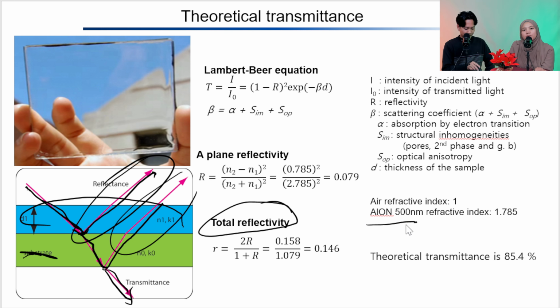And we can see here, as I mentioned, when we use... You talk about thickness. Yeah, it will be reduced. So even with fewer layers of the transparent gamma AlON, you can have a higher protection level compared to just conventional glass. Wow, that's so nice. And not only just size, but how helpful it will be when you have a thinner profile of the window, because using transparent gamma AlON is very helpful, I think, in many